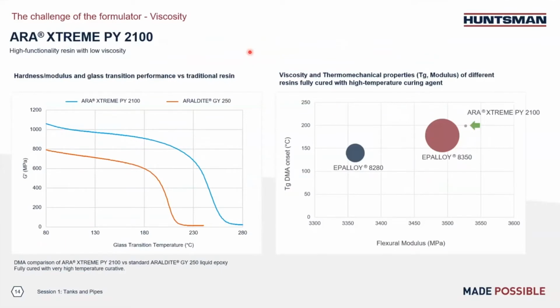So now here's more data about XTREME PY2100. If we look at the left chart first, we compare PY2100 with Araldite GY 250, which is a typical standard bis-A type epoxy resin. Like I mentioned earlier, PY2100 has higher functionality. So in this test, in both G' and glass transition temperature, we can see PY2100 gives much better performance.